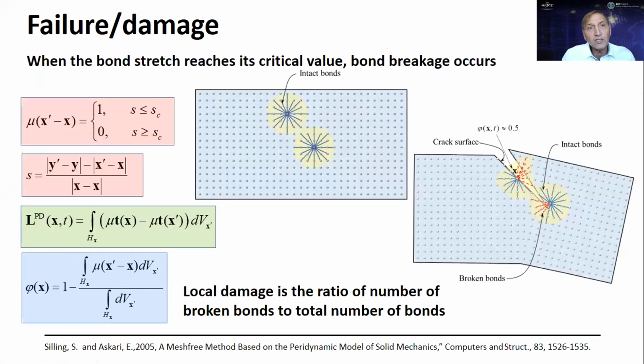So how do we handle damage? As I mentioned before, we monitor what goes on between these two points, X and X prime. And when the stretch reaches a critical value, we break the bond. And the stretch is defined in a very simple way: the final length minus the initial length divided by the initial length. And we have a status parameter mu. If the stretch is larger than the critical stretch, then the status parameter becomes zero. Basically, in the internal force vector here, the contribution, the force, goes down to zero, right? If it's intact, we have one.